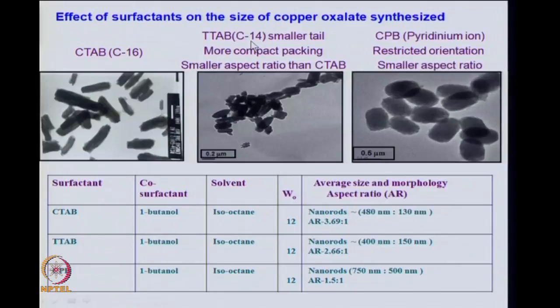So, this is more or less what we discussed already. If you have a C16 carbon, C14 carbon, this is a larger tail hydrocarbon chain, the smaller hydrocarbon chain, more compact packing, there is a smaller aspect ratio. If you have CPB, which is a pyridinium ion, you have a restricted rotation and you get smaller aspect ratio. So, these numbers we have tabulated. When you have C-tab or another surfactant T-tab, so you are varying the surfactant, keeping the co-surfactant same, the solvent is the same, the W naught parameter is the same. So, only variation is in the surfactant and you get variation in the average size and morphology or the aspect ratio, which is the ratio of the length to breadth, and that changes like going from 3.7 to 1, to 2.7 to 1, to 1.5 to 1 by changing the dimensions of the surfactant.